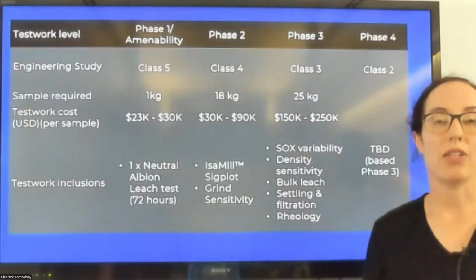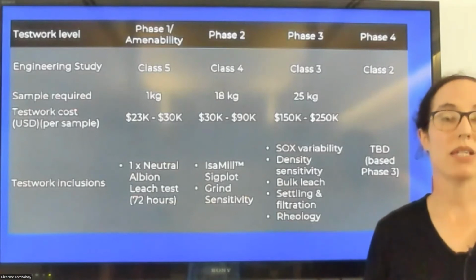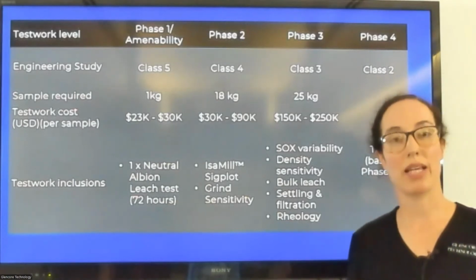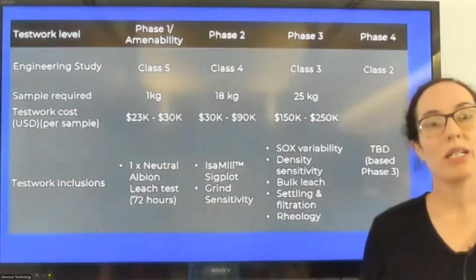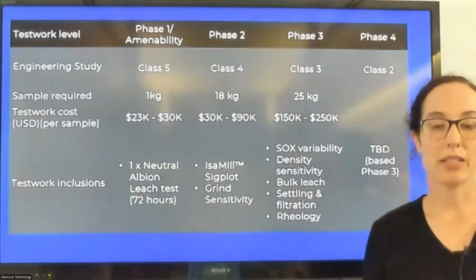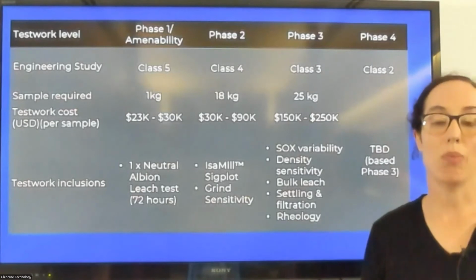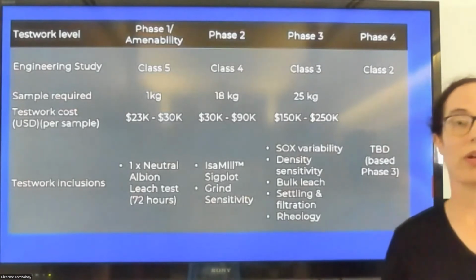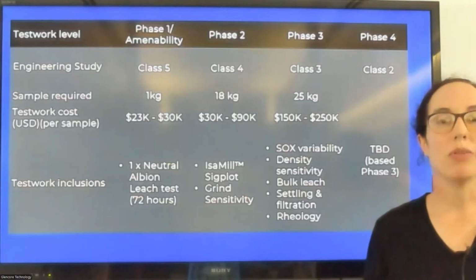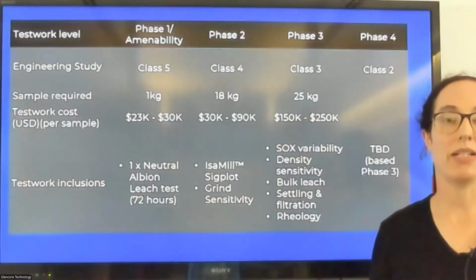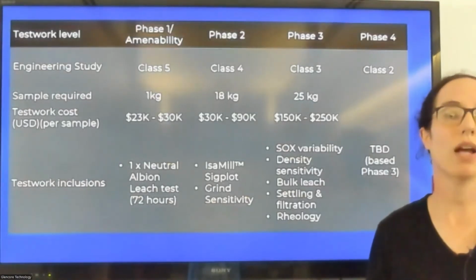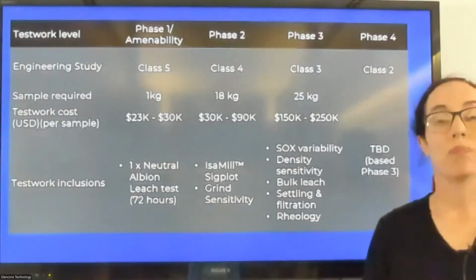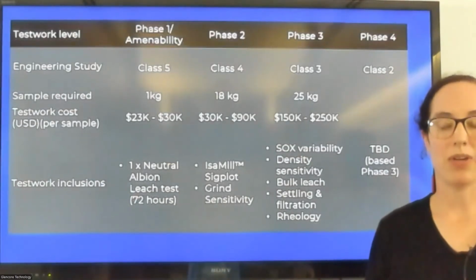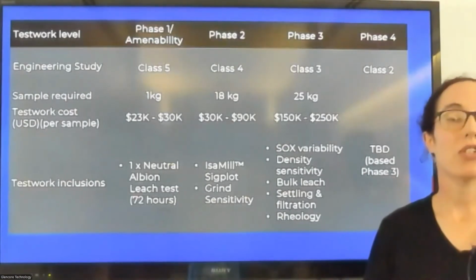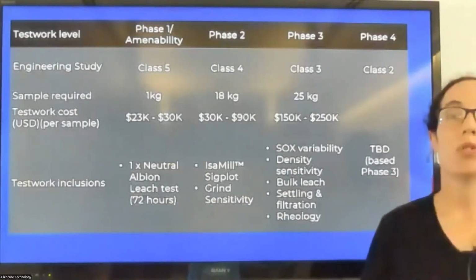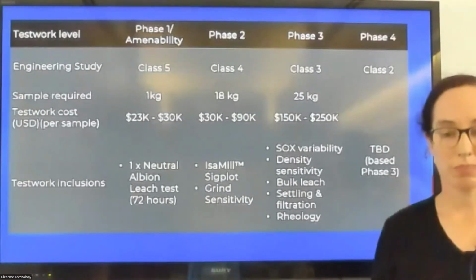This is because phase 2 looks at the grinding section of the Albion process, and phase 3 looks at the leaching portion. So ultimately, all phases would need to be conducted. If a combined phase 2 and phase 3 test work program is being done, it would be very important to ensure that the sample provided is representative of the life of mine or the life of the project. One of the benefits of splitting up phase 2 and phase 3 is that you get an even spread of expenditure for your test work.